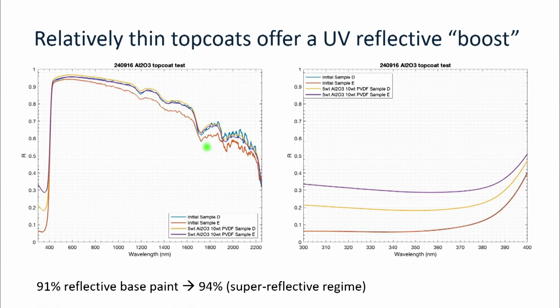You don't need to worry about all these details. This is wavelength, and this is the UV part of the spectrum. And what we're showing is that as we increase the amount of that top layer, we can, by design, increase its UV reflectivity and therefore its total performance. And so this is a mechanism for us to take a 91% reflective paint you can buy commercially today up to 94% and even maybe the 97% super reflective regime at an extremely low cost, and we think in an extremely practical way.